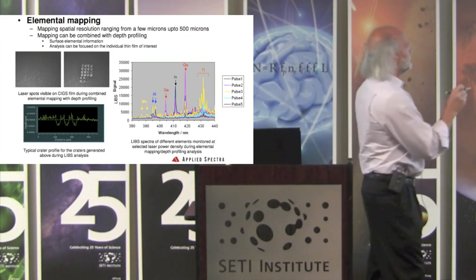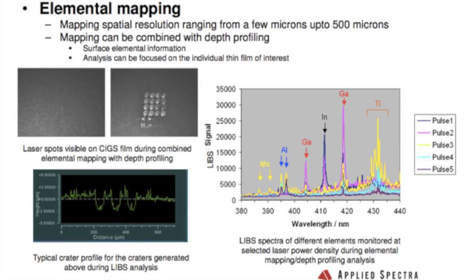Here's something else you can do. You can look at it. This is mapping of a surface as well as into the surface. This happens to be a bulk elemental analysis. I had to scrub some of these because they come from some of our customers. Okay, this is a CIGS film. This is a solar material, copper, indium, gallium, selenide material. And they just wanted to see the homogeneity across the surface of this solar material and into the depth. So here we're looking at things like aluminum, gallium, indium, titanium, moly. And again, this is a function of depth versus on the surface. So you can do surface mapping, you can do depth profiling.